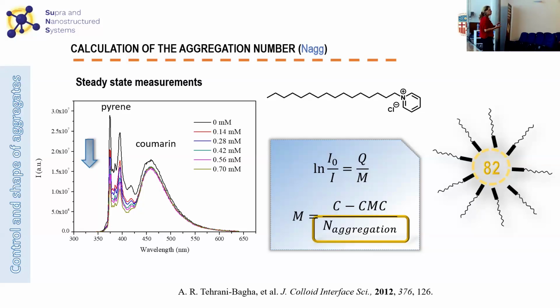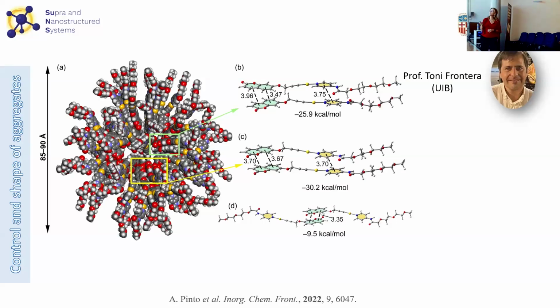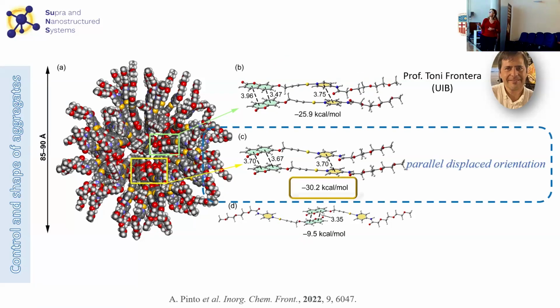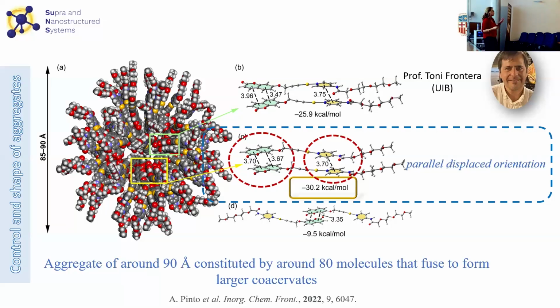Finally, just to predict what type of interactions are present in this large assembly, we went to a collaborator at the University of the Balearic Islands, Tony Frontera, and he made some calculations that could perform different types of assemblies between the molecules, and it seems that the most stable one is this pi-pi stacking between the coumarins, a little bit shifted. But it also confirmed that these 80 molecules match the sizes that we could record with the other techniques. So this is a little bit of an overview of all the techniques that we can use from the beginning to the end to detect and determine the structure of our supramolecular assemblies.